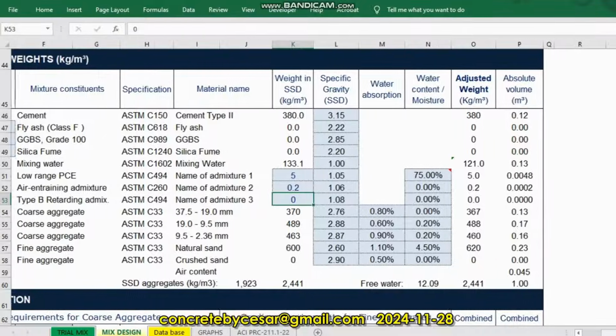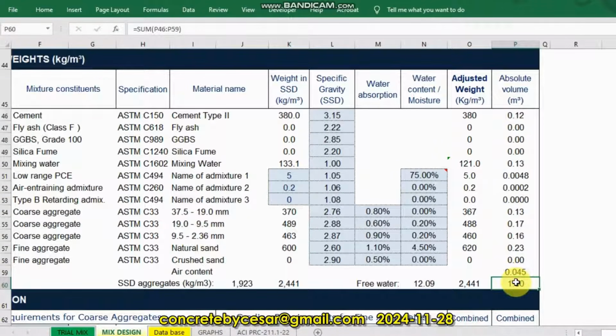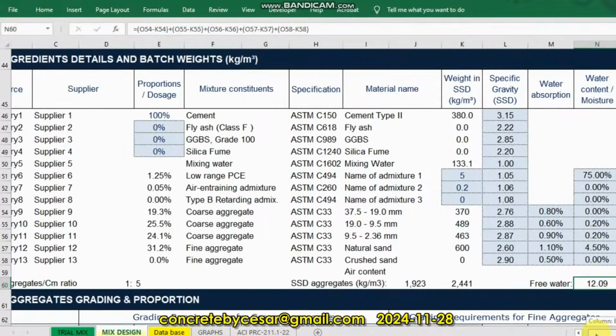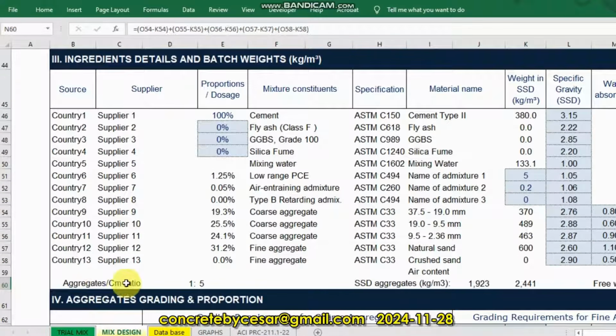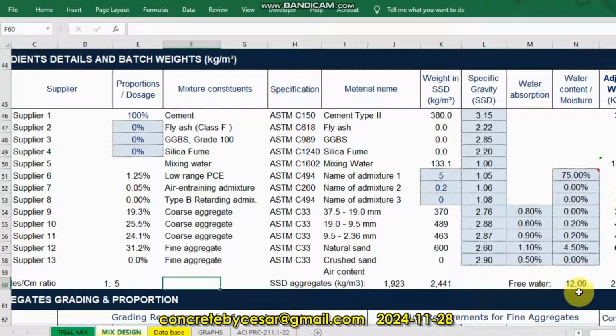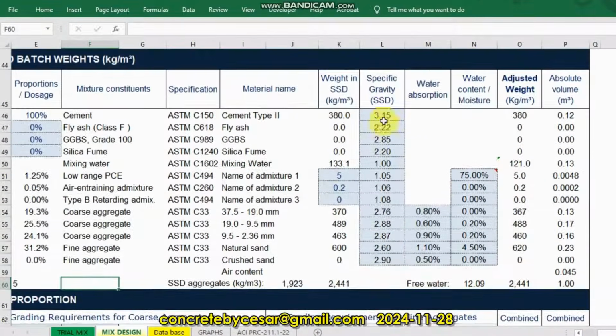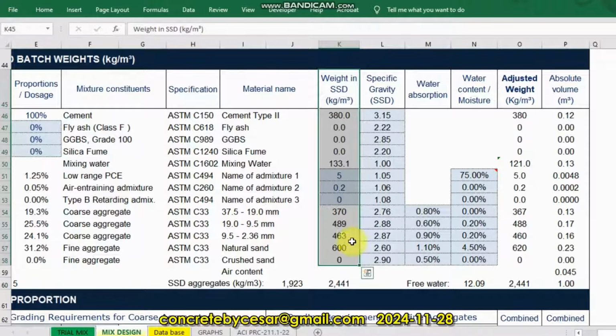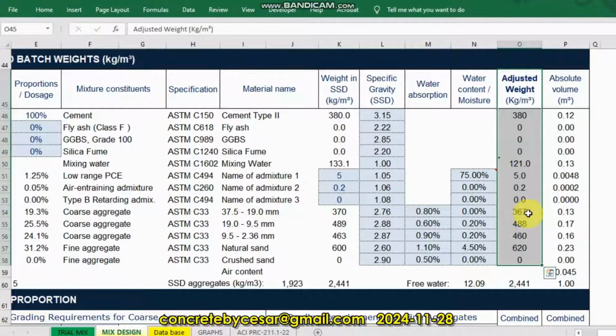So I need to just explain a little bit more. So here the absolute volume is 1 cubic meter. Very self-explanatory. The weights of material in SSD aggregates, 2441, has to be equal to the adjusted weights, 2441 as well. The free water is 12 kg, so you have to deduct it due to the moisture as well as the water content of the mixture. Our aggregate cement ratio is 1:5, so it's very normal. So basically this is our final design value in SSD condition, and this is the adjusted weights based on the actual condition of your aggregates.